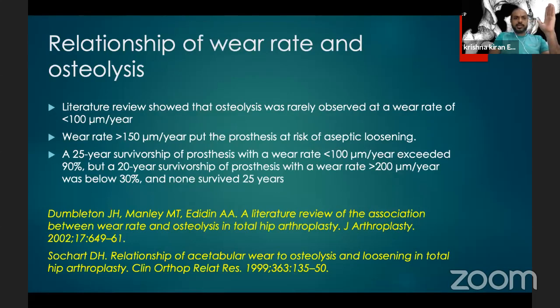And there is a relationship of wear rate and osteolysis. Literature review has shown that osteolysis is rarely observed at a wear rate of less than 100 microns per year. So that is the osteolysis threshold for a hip. And a 25-year survivorship of prostheses has been observed where the wear rate is less than 100 microns per year. This is with the Charnley hips, but when the wear exceeds 200 microns per year, then the 20-year survivorship of the prostheses was below 30%. So this is a very important concept.